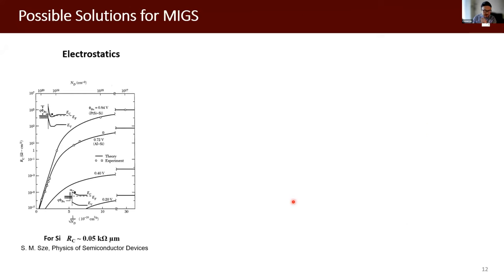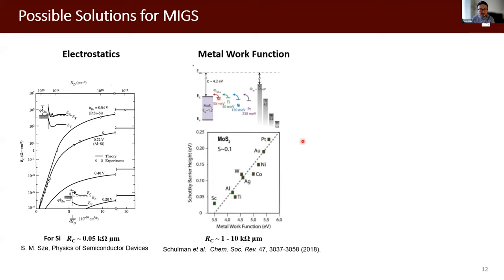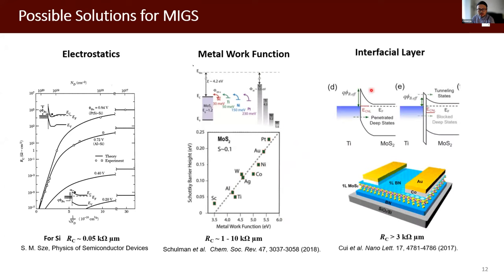Previous work has demonstrated several possible approaches to reduce the contact barrier. For example, using electrostatics by heavily doping the semiconductor side, you can introduce more tunneling current and thus less resistance. The second approach is to find a more exotic material that can have either a very low work function for N-type contact or a very high work function for P-type contact. But as I mentioned, the tuning is very weak, so this is not a very ideal approach. The third one is to decouple the interfacial hybridization by inserting a very thin dielectric tunneling layer. But at the same time, this tunneling layer also blocks the current, so there is also a trade-off. None of these approaches really solve the problem very well, and they are especially not acceptable in 2D semiconductors.